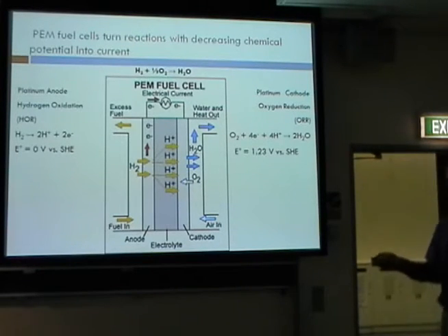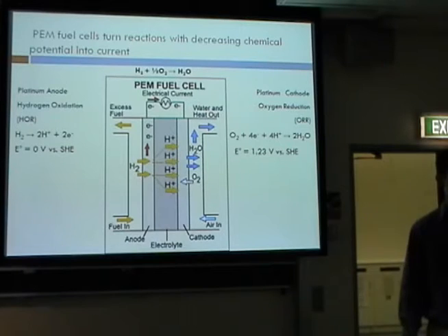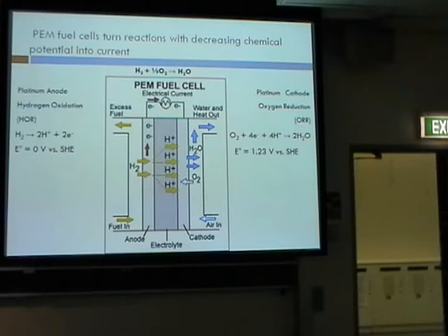And another disadvantage of the current membrane is that you have to keep it very hydrated in order to transport protons and keep it from becoming overly brittle. So you have to feed a lot of water into the reactor during the reaction. And so those are really the 2 key issues, and we'll focus, since this is a catalysis presentation, mostly on the fact that this reaction is slow and what people are trying to do about it.